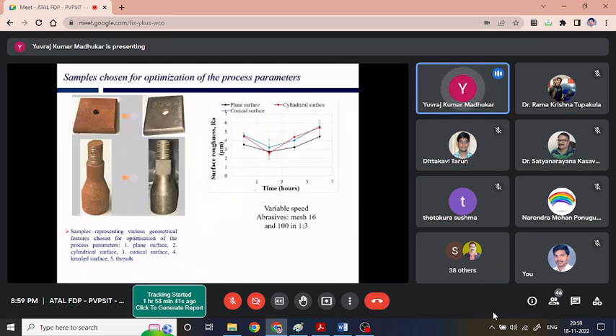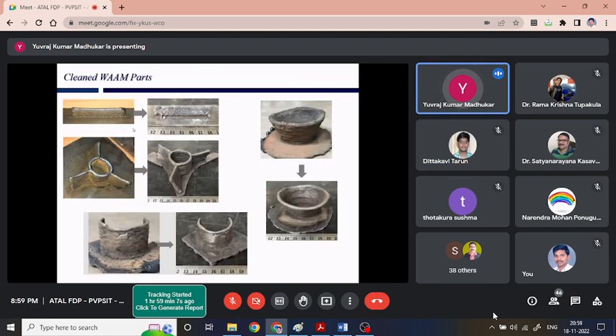To optimize how many hours or minutes we should clean, we should optimize the parameters again, with a certain rotational speed of course. We can take a standard shape like this, and within a time duration of 1.5 hours or so, we could see it completely cleaning the surface. So within 1.5 hours, possibly we can clean one part as well.